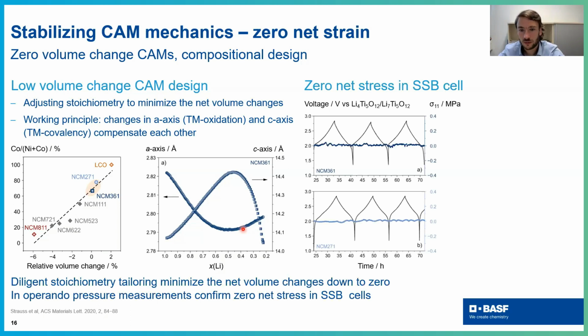And if you then build a solid state battery and measure the pressure during the cycling, then you see that for both these materials, so these are NCM271 and NCM361, you actually do not measure significant volume changes during the charge and discharge, which is very nice.